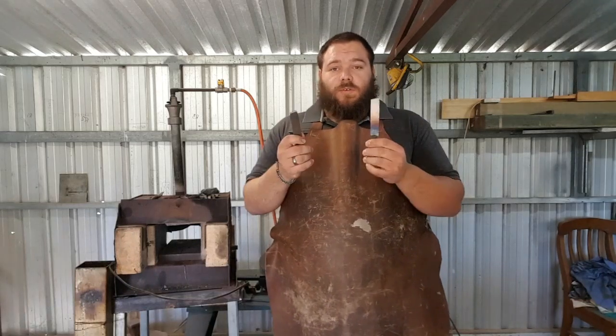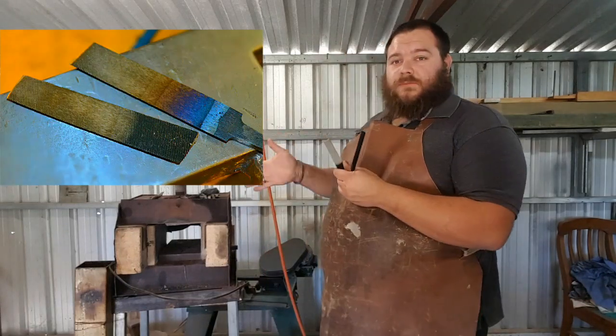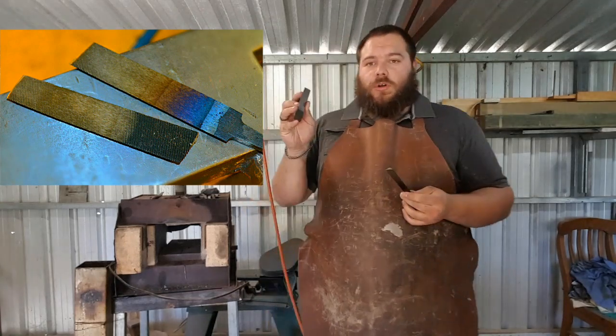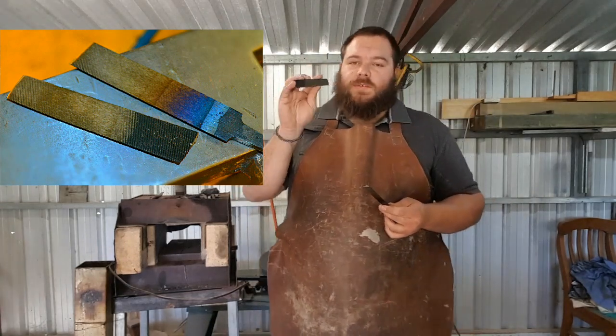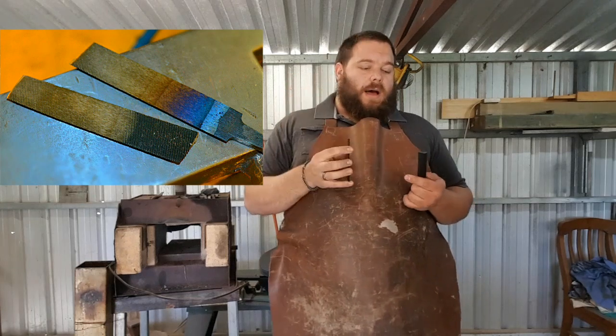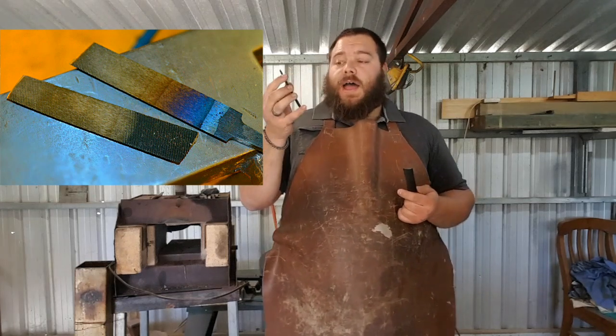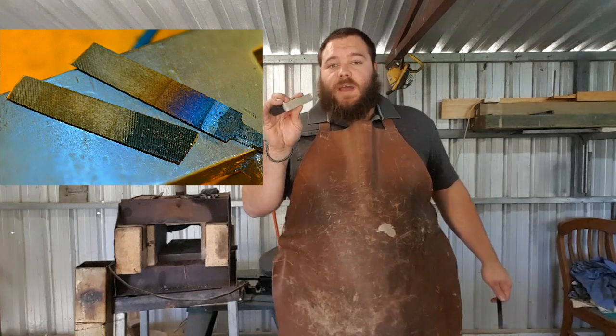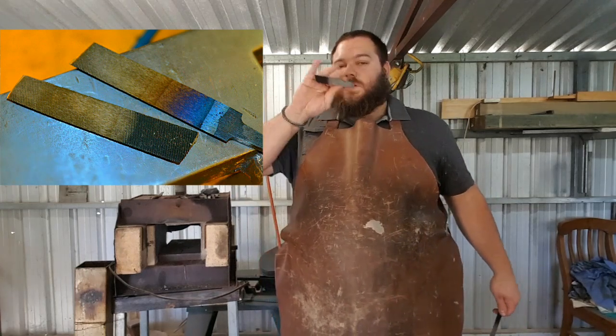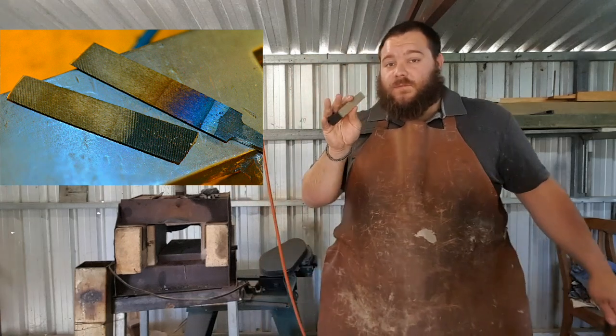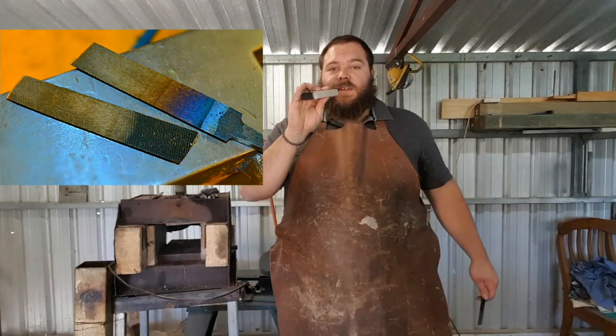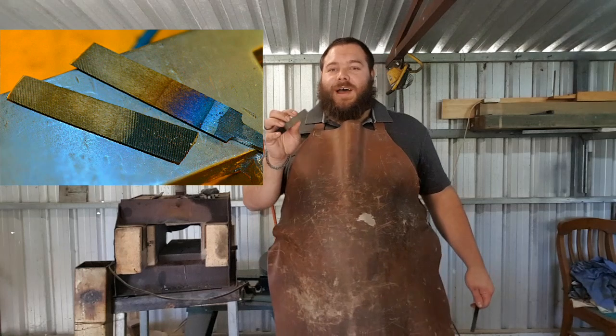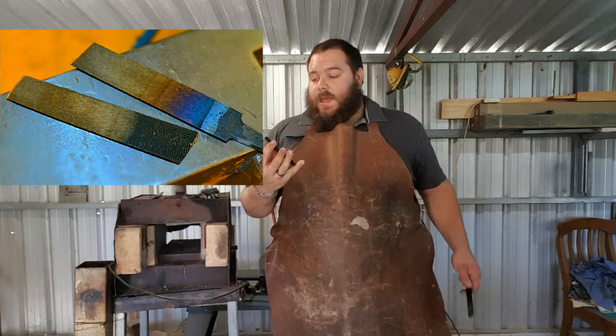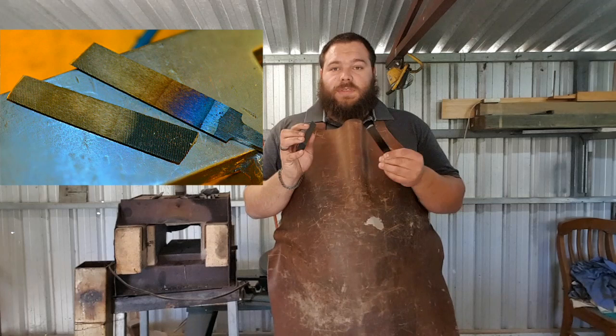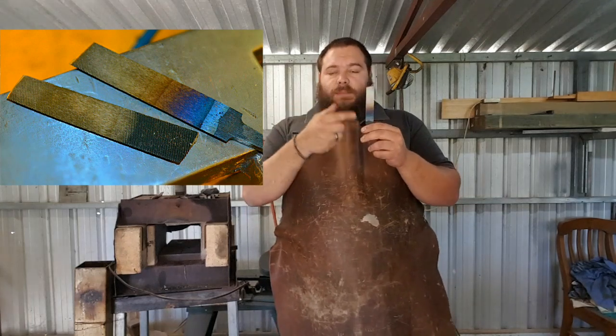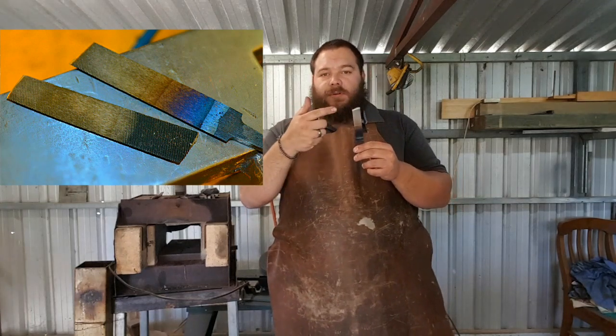Okay, so we've got the two items out of the temper. I'm going to put a photo up here. You'll notice that the oven tempered one hasn't got as much of a colouring to it because I only tempered it for half an hour, and also because it was in the environment of the oven, the oxygen was actually getting expunged to a certain degree, so the oxides didn't form as well. It actually started to colour a little bit more after I took it out of the oven than it was inside the oven. But the important thing to note is, obviously, the temperature range on the torch tempered one is